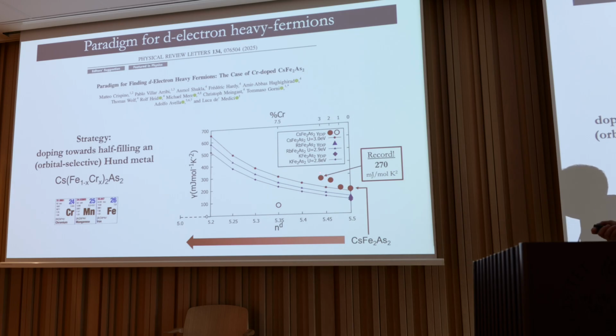This is not the highest d-electron heavy fermion we know, since lithium vanadium 2 oxide 4 had 420, but it still tells you the mechanism we are trying to push works—you can enhance the heavy fermionic behavior by doping further towards half-filling. Then at some point something else happens: for another composition they synthesized, 7.5%, there's a complete change of behavior, and the Sommerfeld coefficient goes down.